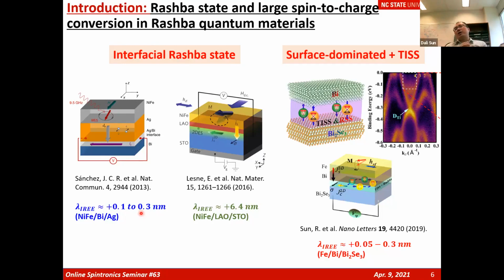Actually, that's one advantage of the Rashba state for spintronic applications, because by tuning the strength of the Rashba state by applying a gate voltage, or maybe any electric field, the spin-to-charge conversion efficiency can be tuned from positive even to negative, giving an electronically tunable spin-to-charge interconverter, which can be used for spintronics applications. So that's what has happened in inorganic systems, inorganic semiconductors, and metal systems.